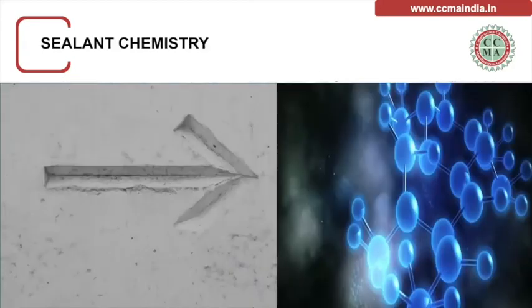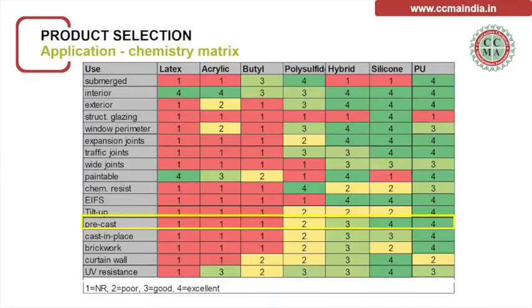Now, selecting the right chemistry for the sealing job. In this table, you will find various chemistries that have been rated depending upon the suitability for a particular application. So if you see the yellow box for the precast, the various chemistries have been rated. A rating of 1 means not recommended, and a rating of 4 would be excellent. So latex, acrylic, and butyl are a strict no-no for the precast joint. Polysulfide would fare poorly, and the best choice would be silicone and PU.